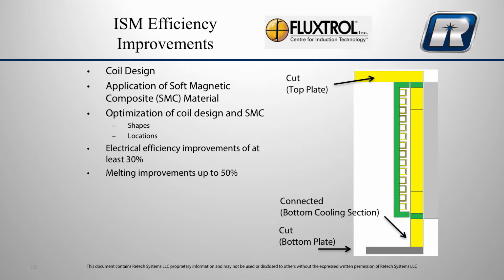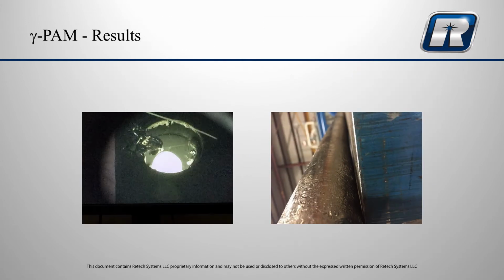So far we've seen electrical efficiency improvements of at least 30%, which is a big deal for cold wall induction melting. And in some cases, not in all, melting improvements of up to 50%. We melt 50% faster is what we mean by that. Shown here on the right is a basic diagram of how we modeled the system at Fluxtrol and took the results and applied them to practice.